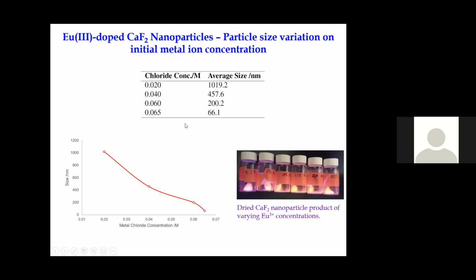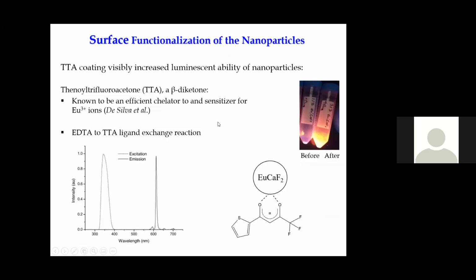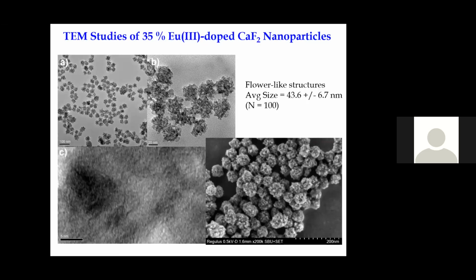Now, we've done a lot of work here. We've changed the initial salt concentration, which fine tunes the size of the nanoparticles. We've done the coating of the nanoparticle with that ligand. You see, they are glowing. They emit luminescence, so we are seeing the same concept with these materials as well, the energy transfer mechanism that we were talking about. These particles are about 40 nanometers, and you see they have a rough surface. They are flower-like. In figure C, you see the lines. I don't know how clear it is, but in some areas there are lines, and those lines are groups of atoms. So we can now even see groups of atoms using these high imaging technologies.